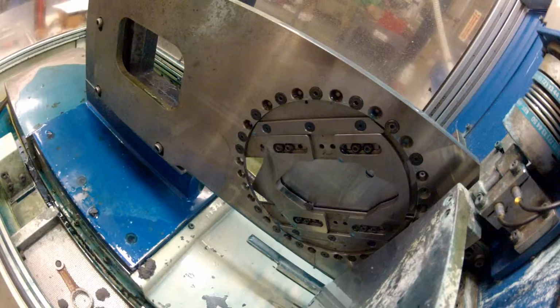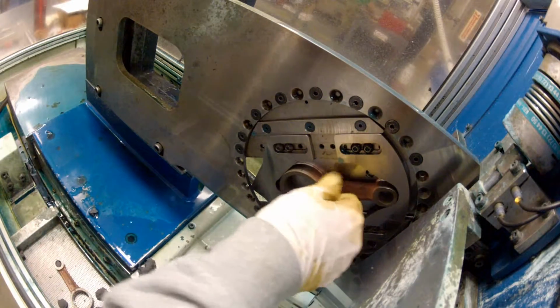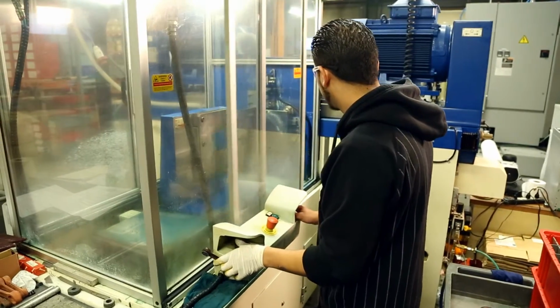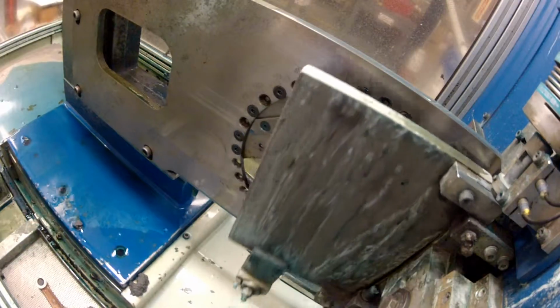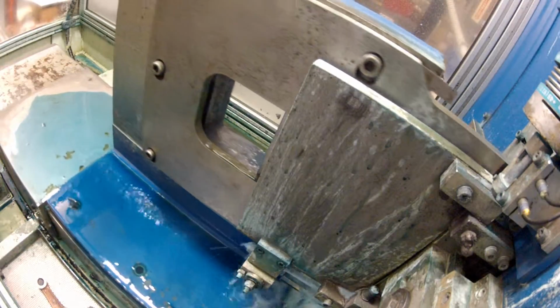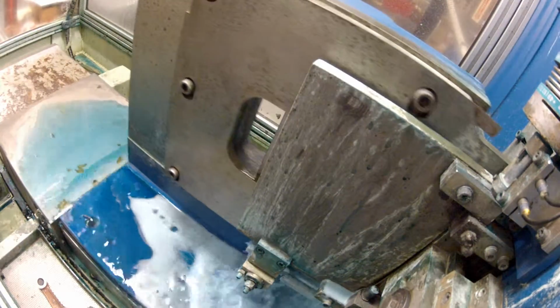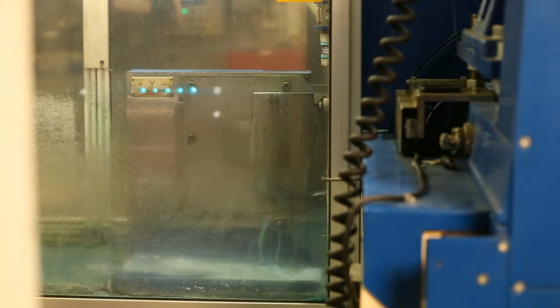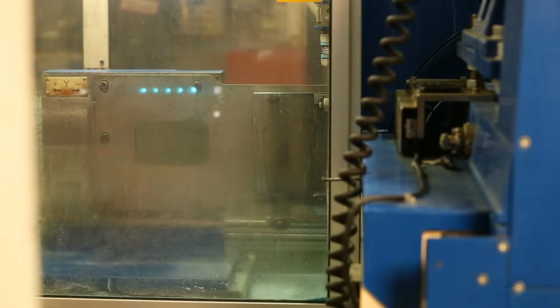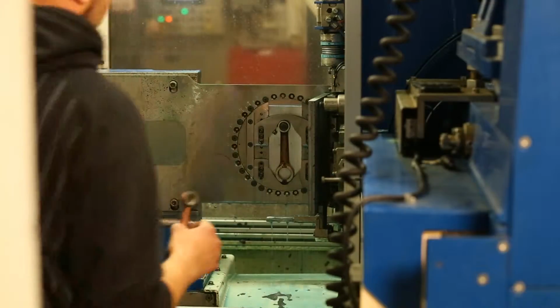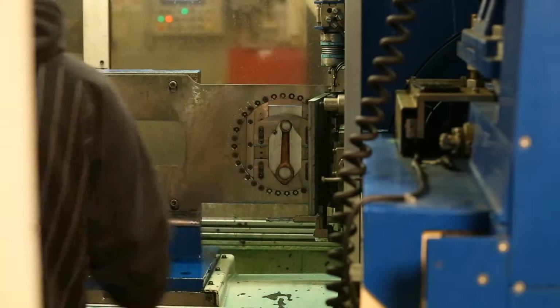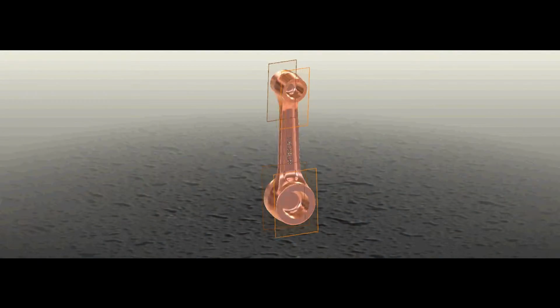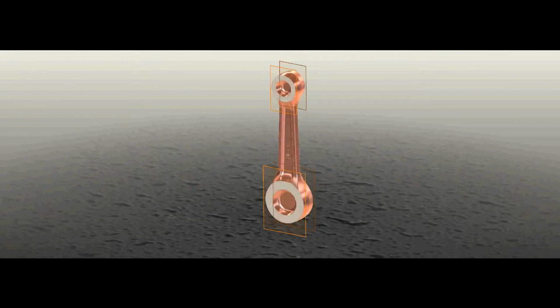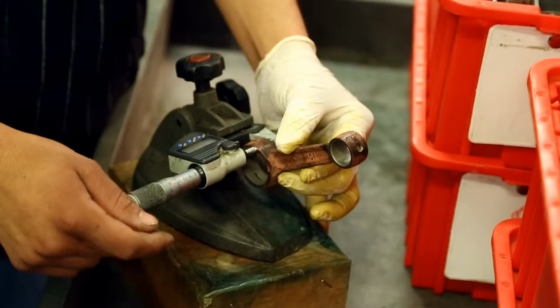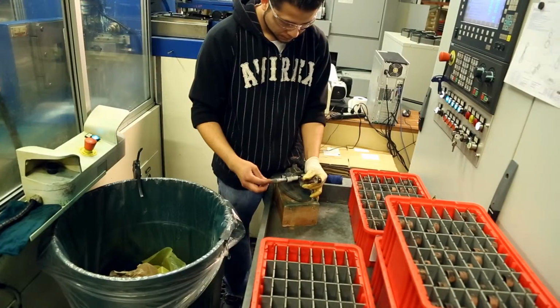finished, ground, and honed. After heat treatment, the rods are returned to be finished ground to their final specified width. Going through the CNC grinder a second time, this last grinding process is the most critical to ensure the rod surfaces are perfectly straight, because after heat treatment, the surfaces become distorted. The grinder makes each surface perfectly flat within 5 microns or 2/10,000th of an inch, and each part is hand inspected by the operator with a micrometer for overall dimensional consistency.